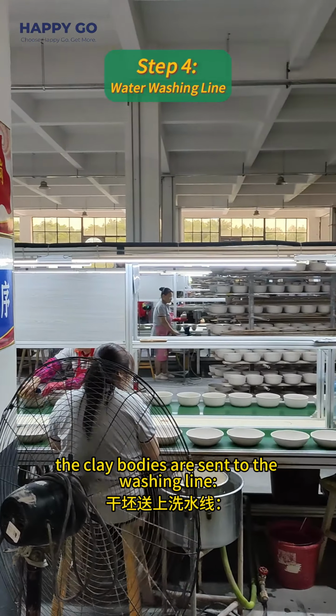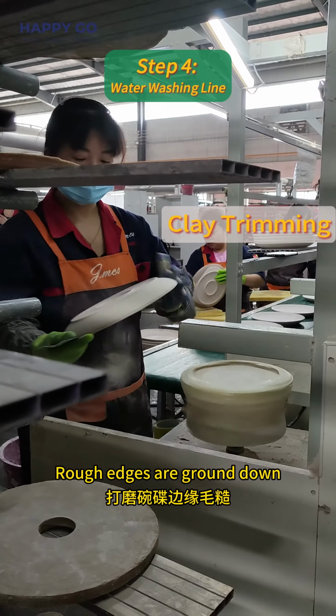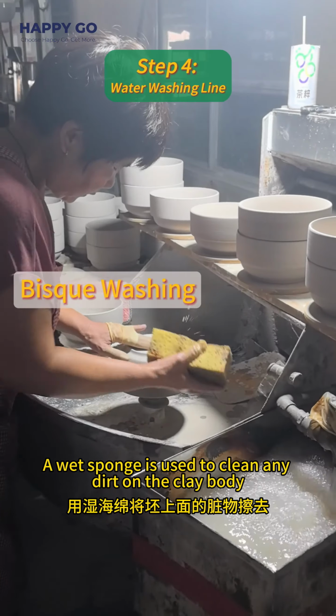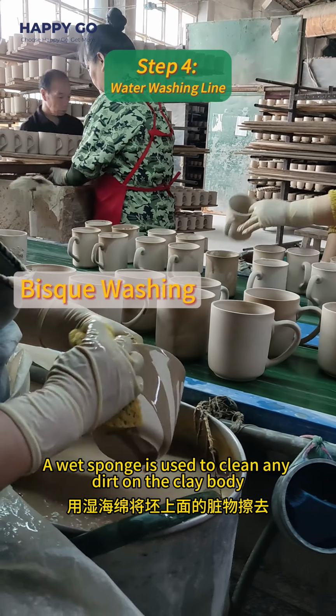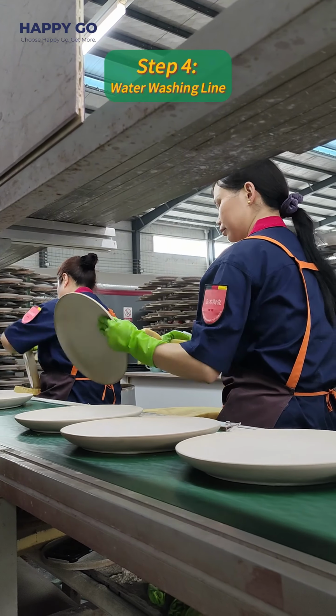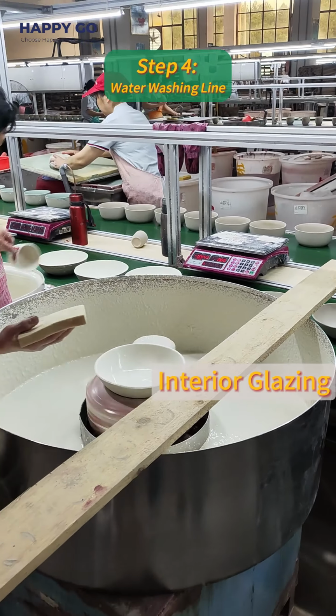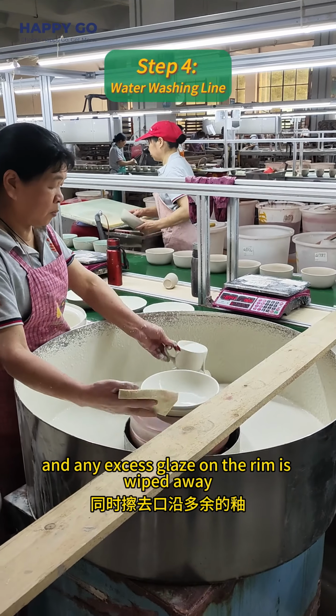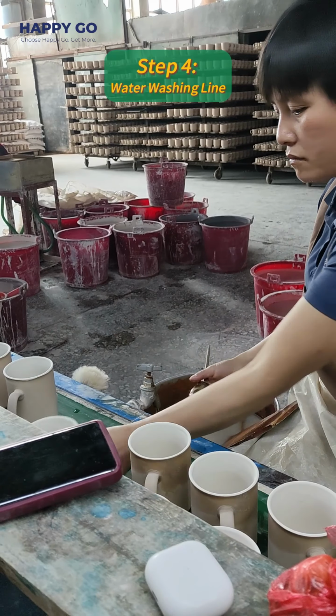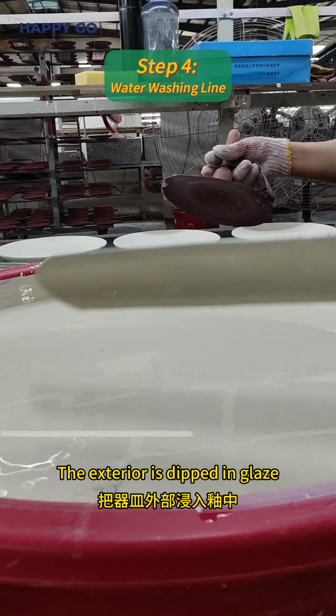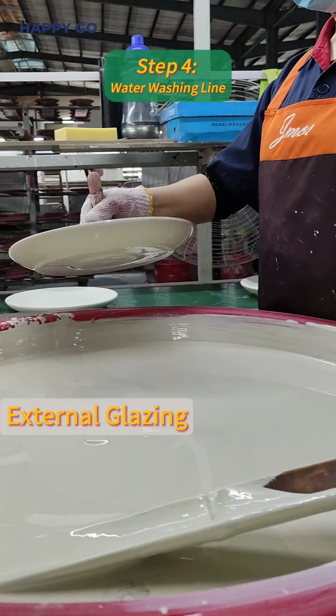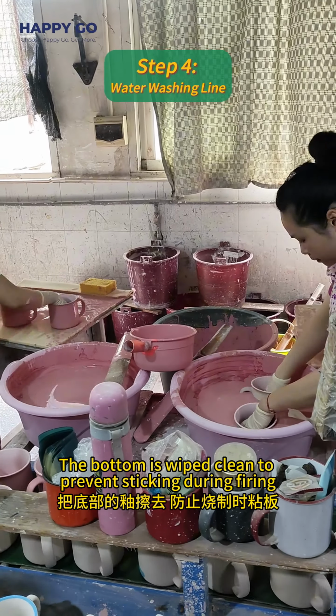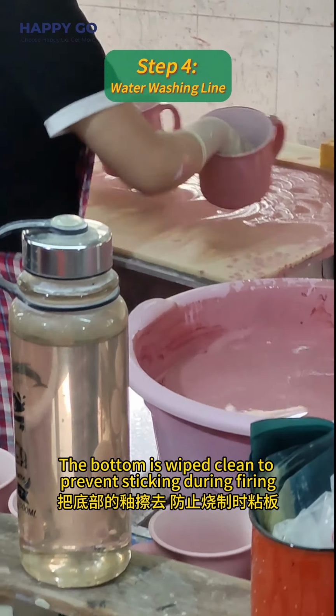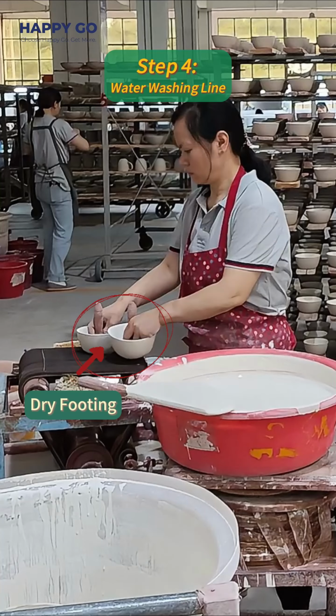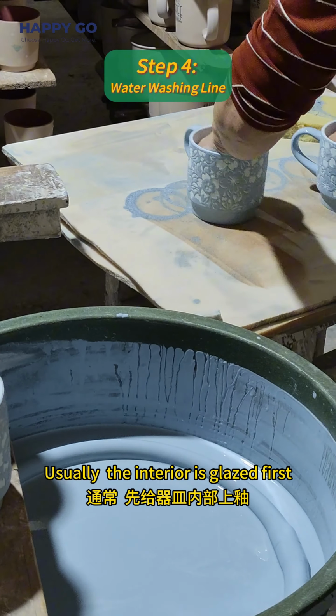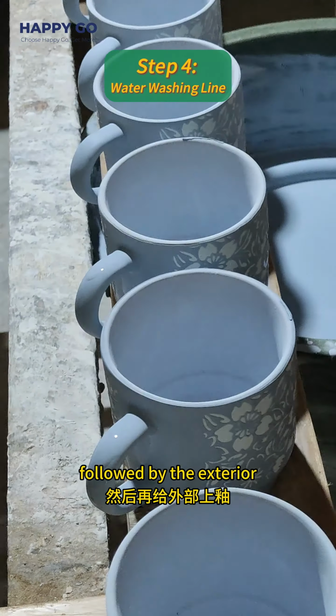Once dried, the clay bodies are sent to the washing line. Rough edges are ground down. A wet sponge is used to clean any dirt on the clay body. The inside is glazed, and any excess glaze on the rim is wiped away. The exterior is dipped in glaze. The bottom is wiped clean to prevent sticking during firing. Usually, the interior is glazed first, followed by the exterior.